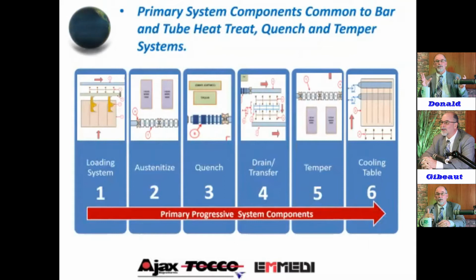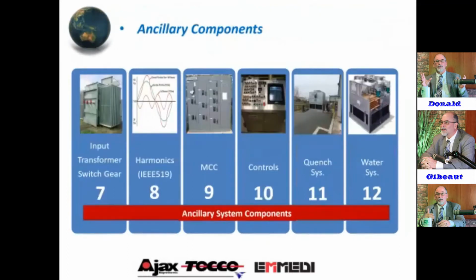Then we go into a temper section to adjust the hardness and the ductility with reheating. Then it has to cool in air, so it goes onto a cooling table. Typically our systems use a drag chain, and the pipe is on there for hours. Then we get into the ancillary supportive equipment of the line, which is what we covered: the input transformers and switchgear, and harmonic filters.